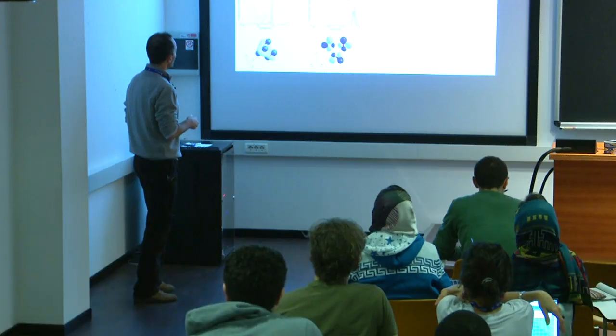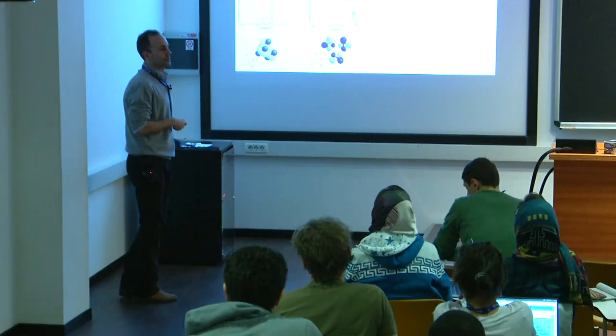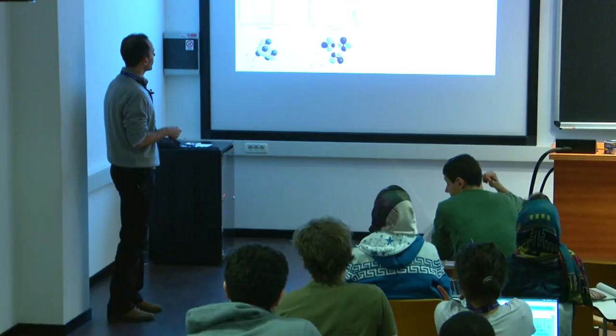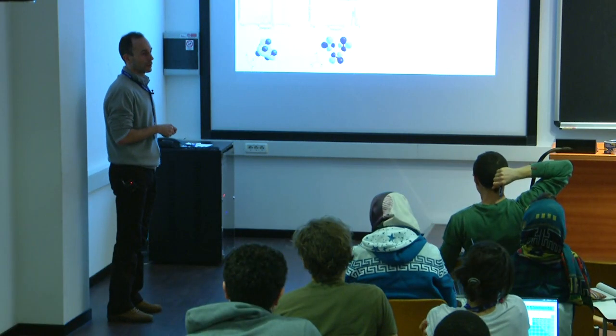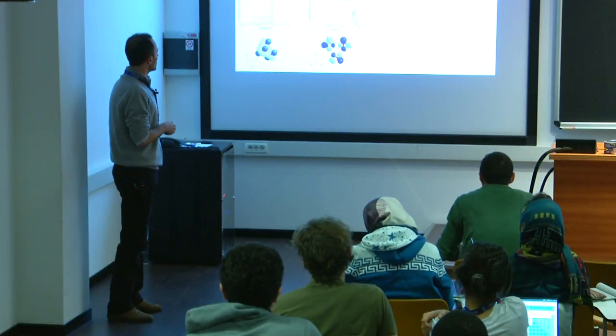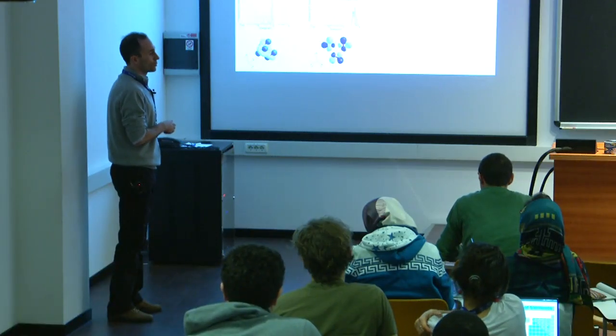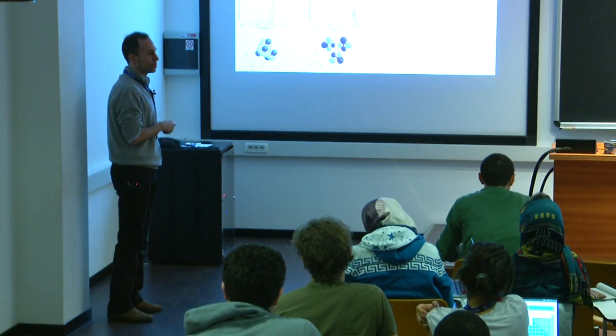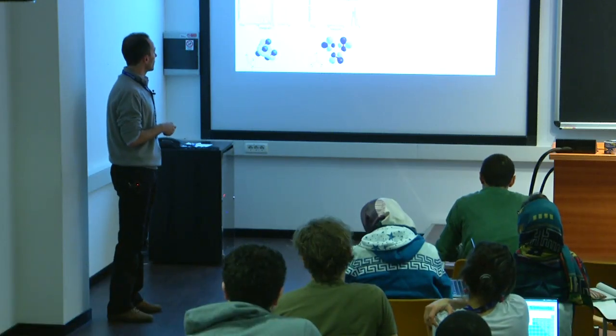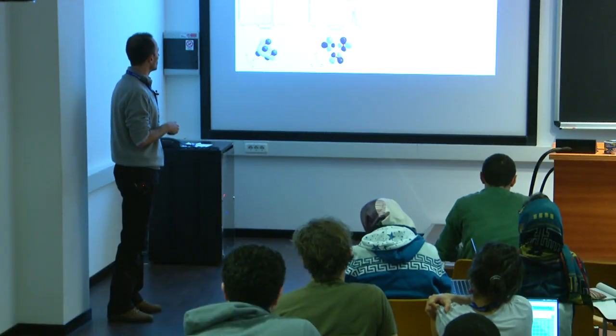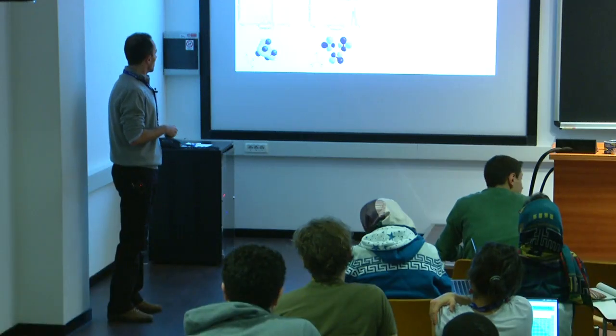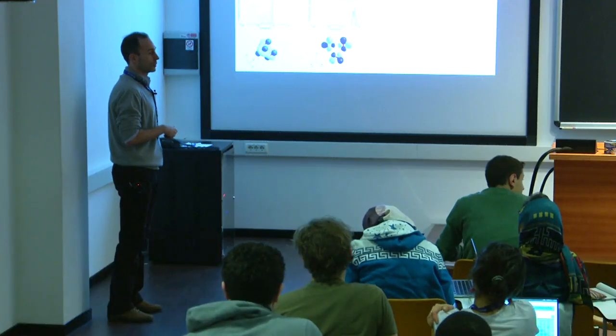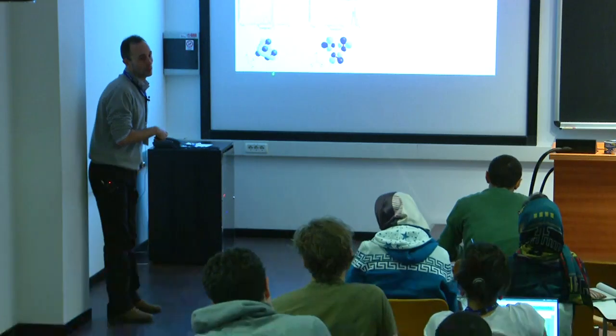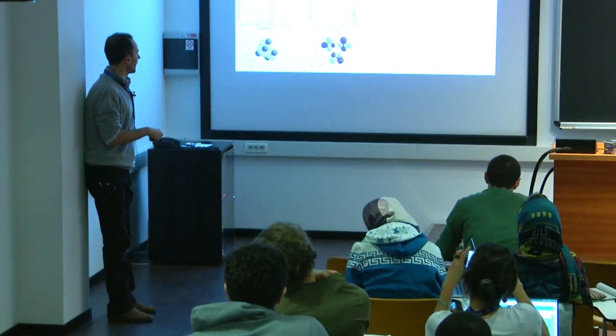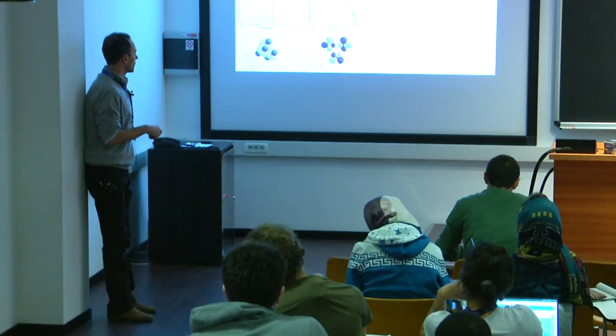What if the metallic state that we get from DFT is actually a linear combination of two insulating states? Suppose that the degeneracy of these two states is only true on average, while instead we can have two insulating states with equal weight, where you localize the electron on either one of these two, like I showed you here. You get a different symmetry state. So the last electrons would localize on a z-square state along the 111 in the first case, or on a planar state on the 111 plane in the second case.